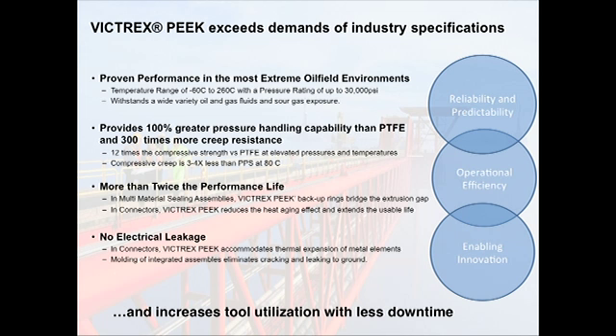more than twice the performance life. In multi-material sealing assemblies, VICTREX PEEK backup rings bridge extrusion gaps, and in connectors, VICTREX PEEK reduces the heat aging effect and extends the usable life. No electrical leakage. In connectors, VICTREX PEEK accommodates thermal expansion of metal elements, and the molding of integrated assemblies eliminates cracking and leaking to ground.